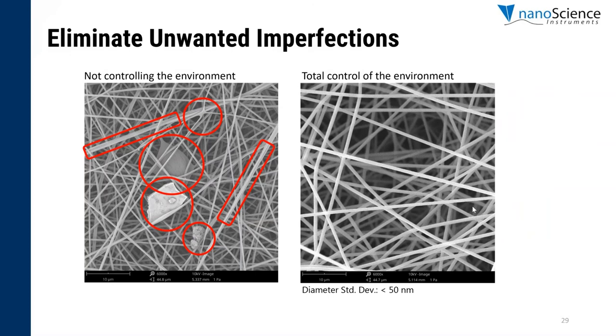So when you control those two parameters, temperature and relative humidity, and also remove the solvents from the chamber, you will be able to achieve perfect nanofibers. Achieving consistent fiber production is so important for multiple applications, especially when batch-to-batch reproducibility and similar results throughout the year are needed. These two images are a clear representation of how the microstructure looks when environmental conditions are tightly controlled during sample production. The left image shows all defects when conditions are not ideal.